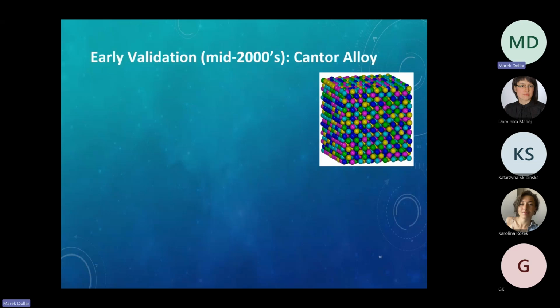It didn't take long. Cantor developed what's today called the Cantor alloy. It's an iconic alloy, if you will, because whoever touches high entropy alloys, that's the starting point. What he did was take five metallic elements, cobalt, chromium, iron, manganese, and nickel, in practically equiatomic proportions, 20-20-20-20-20.